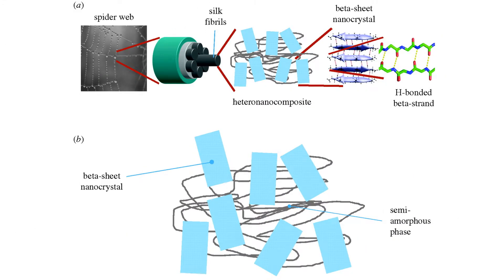The structure of spider silk consists of proteins which contain elastic regions and regions of high strength. One region of the protein is amorphous and thus allows for the elasticity of the silk. Another region of the protein consists of a crystalline structure of beta-pleated sheets. These sheets form a tight crystal structure which allows for the high ultimate tensile strength of spider silk. Finally, a weaker crystal structure of beta sheets connects the amorphous and crystalline regions. These alternate regions allow spider silk to have high elasticity while maintaining a high tensile strength, resulting in an extremely high toughness which validates spider silk's use in ballistics.